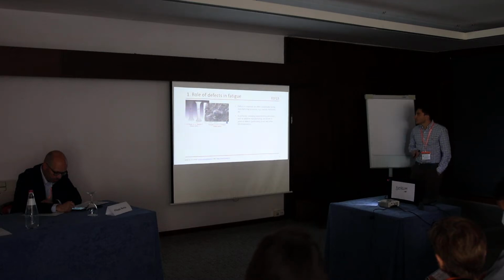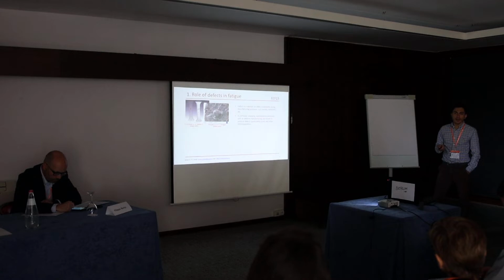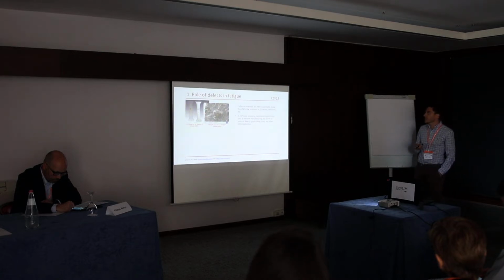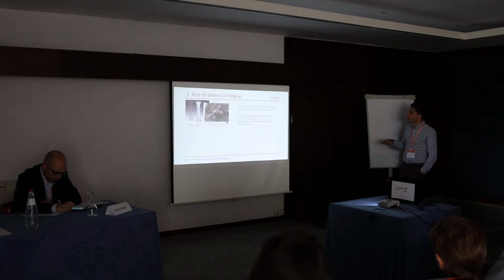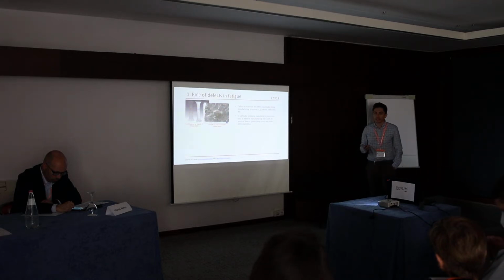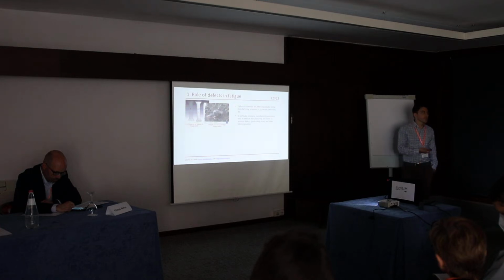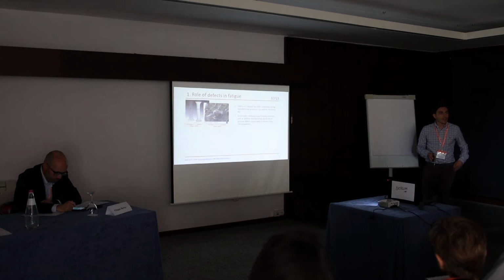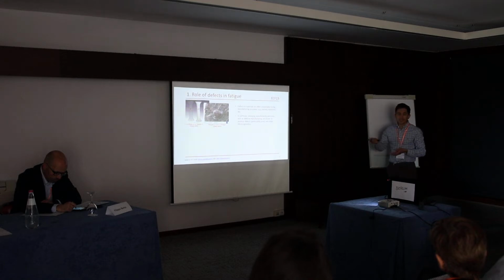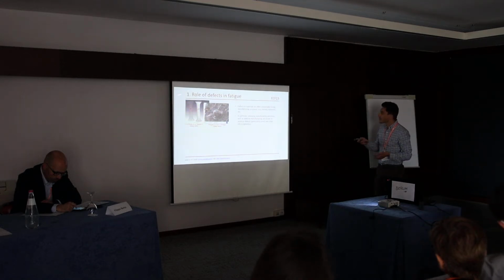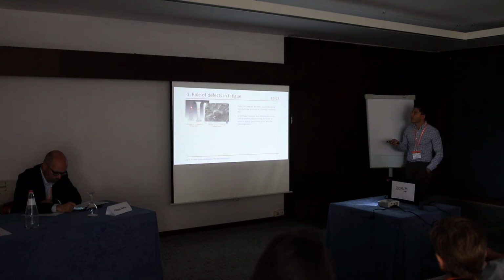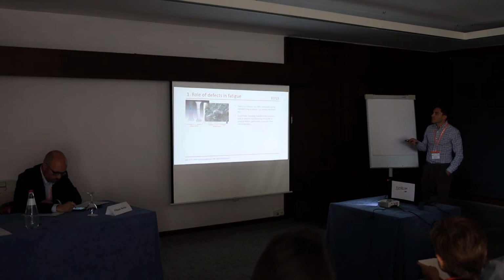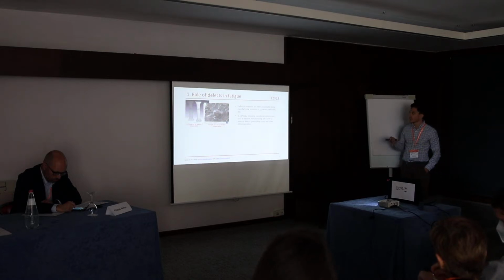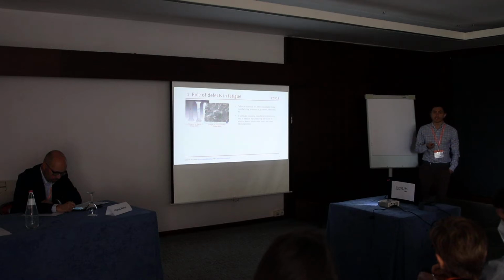Okay, let's talk about the role of defects in fatigue. Defects are always present in materials, because they are due to the manufacturing process, and they can be thought of as porosity, inclusions, etc. We know that for emerging manufacturing processes, it's very common to have defects because they're not mature enough to have a fully homogeneous material. One case is additive manufacturing. We can see from the figure here, from a CT scan, a map of defects, pores, and then a fatigue sample, the fractography of a sample subjected to fatigue, and the crack creation site, which is actually at a lack of fusion porosity.